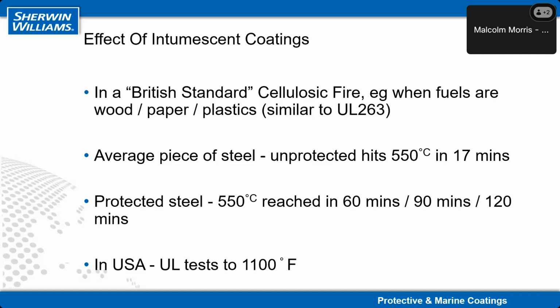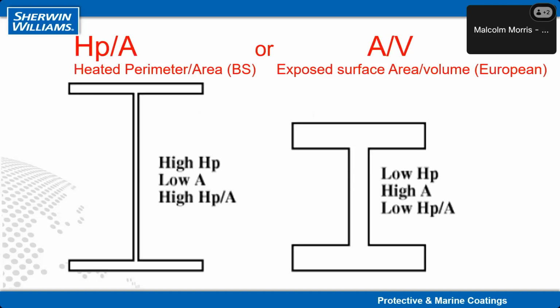In America, it's slightly different because they're still looking in old money, so they're testing to 1100 degrees Fahrenheit. That's the UL, Underwriters Laboratories, testing, but in effect, it's the same concept, no matter which test you are testing to. And the amount of fire protection you need is different to corrosion protection, because, very simplistically, for corrosion protection, the more corrosive the environment, the longer you want it to last, and the more paint you put on. It's not quite as simple as that, but it's independent of the actual size of the steel section you're coating.